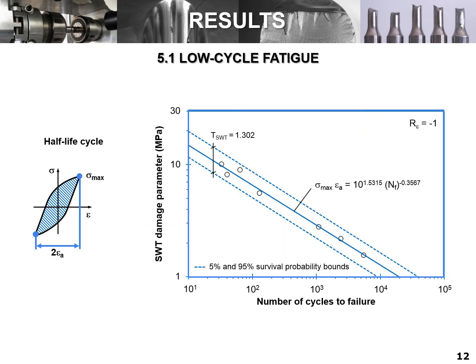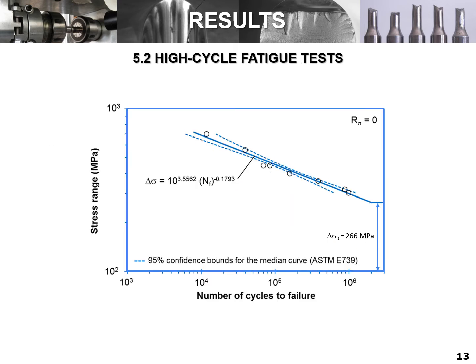Here we can see the relationship between the SWT damage parameter, calculated at the half-life cycle, and the number of cycles to failure. In fact, there is a very good correlation between both variables. This relationship can be fitted by a power function. In relation to the high-cycle fatigue tests, as can be seen in the figure, we also found an excellent correlation between the applied stress range and the number of cycles to failure.